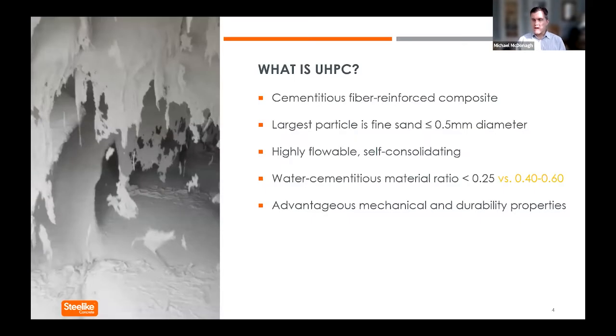So UHPC is ultra high performance concrete. It is a valuable tool for infrastructure durability. And for those that may not yet be familiar with it, it is a cementitious fiber reinforced composite. The largest particle is fine sand, typically less than ½ of a millimeter in diameter. It's highly flowable and hence self-consolidating, has a very low water to cementitious materials ratio. A UHPC class material is typically limited to a 0.25 ratio versus 0.4 to 0.6 for conventional concretes.